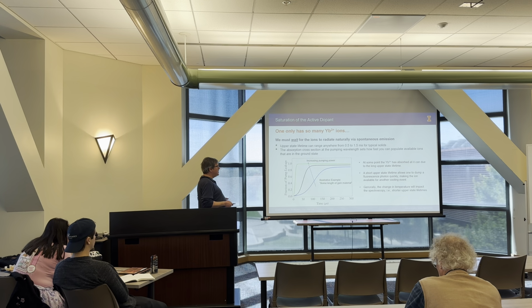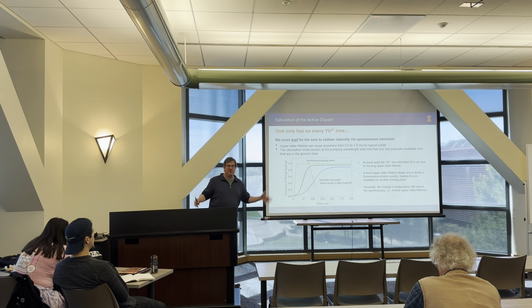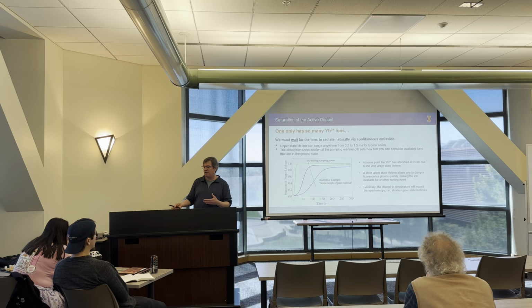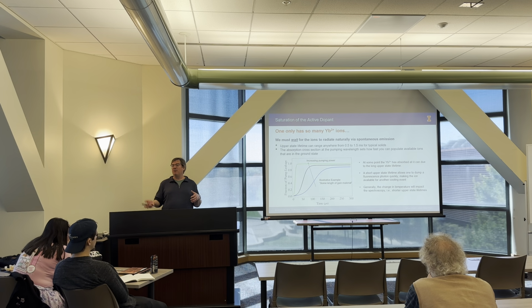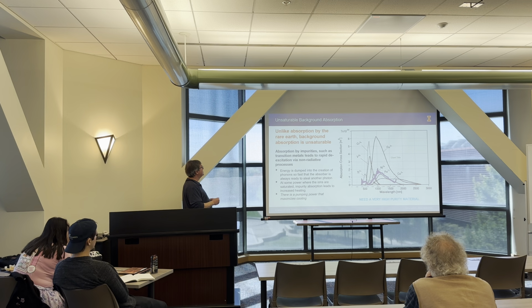And the other thing that's interesting about this is that the change in temperature also impacts the spectroscopy. We talked about Boltzmann. Remember, this thermal population: the absorption and emission cross sections that we see are due to the Boltzmann population of the ground state. If the temperature is different, that distribution is different. So what happens ultimately is you get a narrowing of the spectrum and a reduction in the lifetime. And so as you cool, things get better and better the more you cool. That's a nice, happy thing that happens. So that's the first limitation.